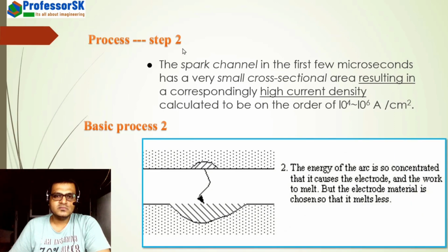Process 2. The spark channel in the first few microseconds has a very small cross-sectional area, resulting in a correspondingly high current density, calculated to be on the order of 10⁴ to 10⁶ ampere per centimeter square. The energy of the arc is so concentrated that it causes the electrode and the work to melt, but the electrode material is chosen so that it melts less. Now in this case, as the temperature has reached up to 10,000 degrees Celsius, the material directly vaporizes, but there are chances that the tool also gets corroded. So that is why the corrosion rate is also more in this process.